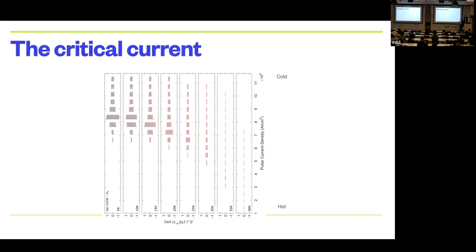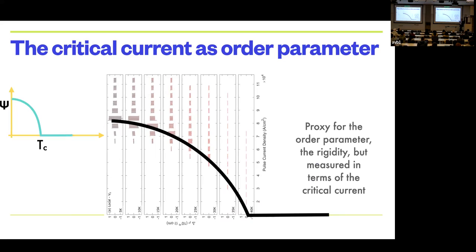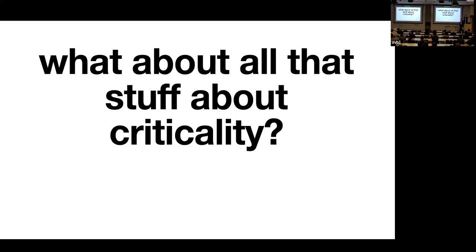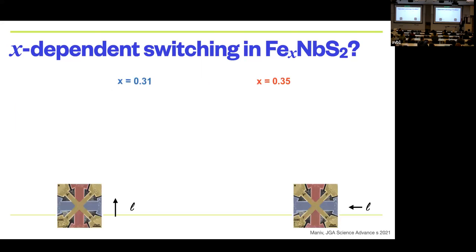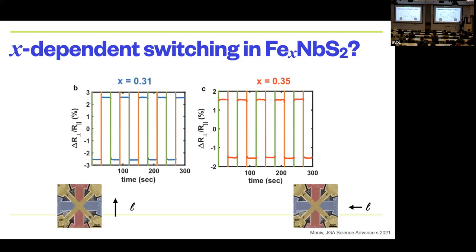You can look at the critical current as a function of temperature, and it basically looks a lot like an order parameter. So it should remind you of that: the current that you need to actually achieve this varies as a function of temperature very much like the order parameter does. So it tells you that it's coupling to the broken symmetry of the system. Okay, but what about this idea of quantum criticality? Why was this relevant at all? Well, kind of. We did notice something very unique about the switching characteristics of the system.